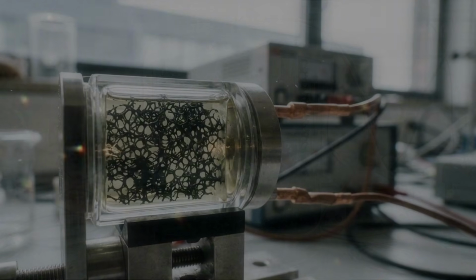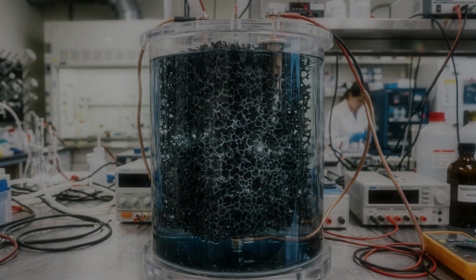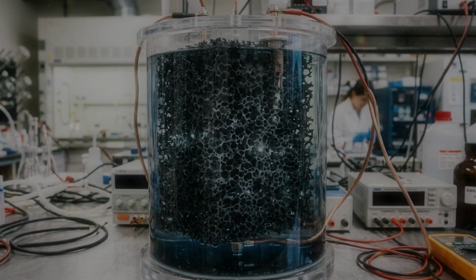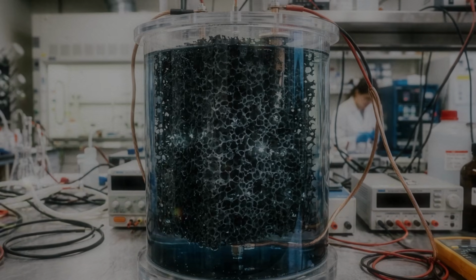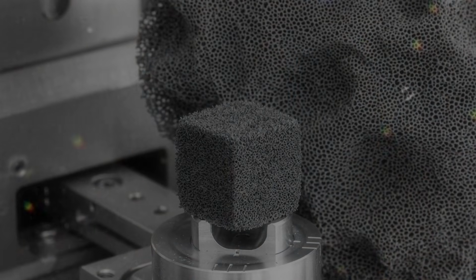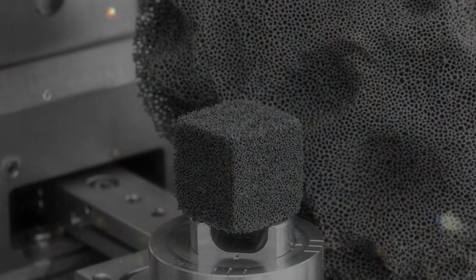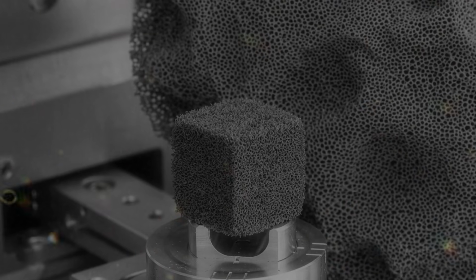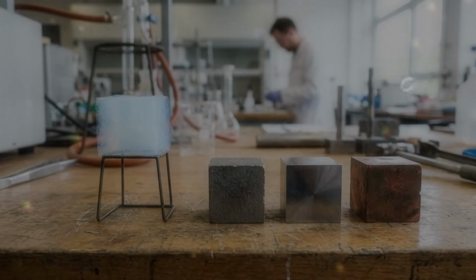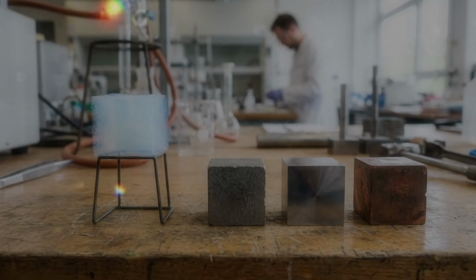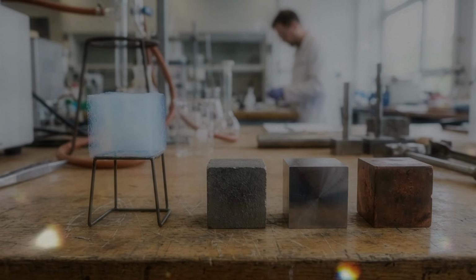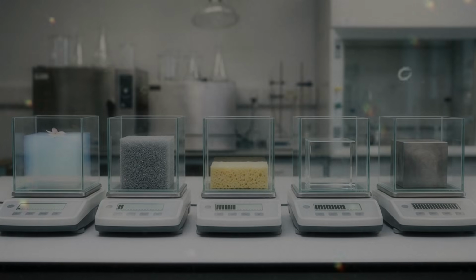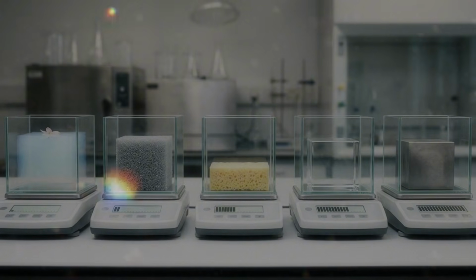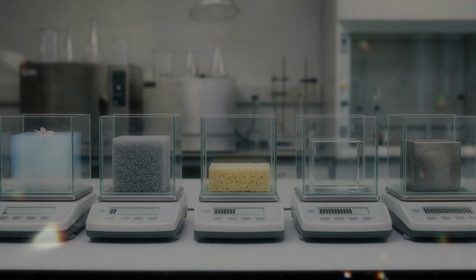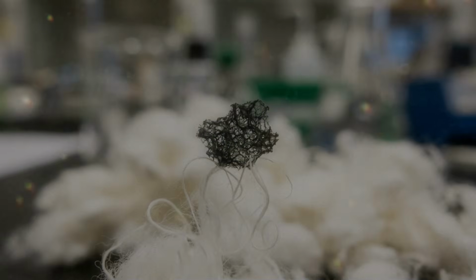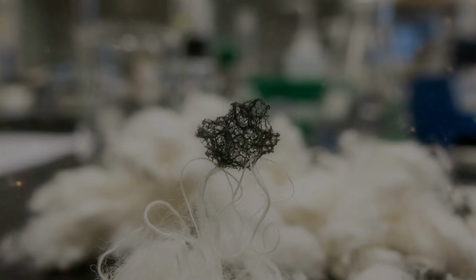The confusion comes from comparing the density of the solid framework and pores with the density of air. An open aerogel does not seal a separate volume of lighter gas in the way a balloon does. The surrounding air can pass through or occupy its pores. Without a closed skin and a useful difference in the mass of the enclosed gas, there is little buoyant lift. The material may be light enough to move in a faint breeze, but that is not the same as floating by itself. It is equally important not to confuse aerogel with ordinary foam.